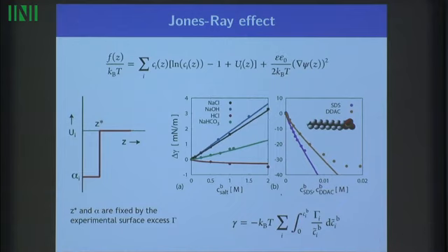And then what we do is we introduce a contaminant, and there are contaminants which we believe would be relatively common nowadays in the environment. So SDS, that's the main component of soap. Yes, so it's a long hydrocarbon tail with a sulfate head group. And there again we look at the adsorption. So this is the concentration of SDS, and again the change of the surface tension. And you can see that these things adsorb very, very strongly. So this goes down to minus 40. So this is linear, and then of course at some point you get micelle formation, so here it's not linear anymore. But the first bit we can fit as well, and we get out this adsorption potential.